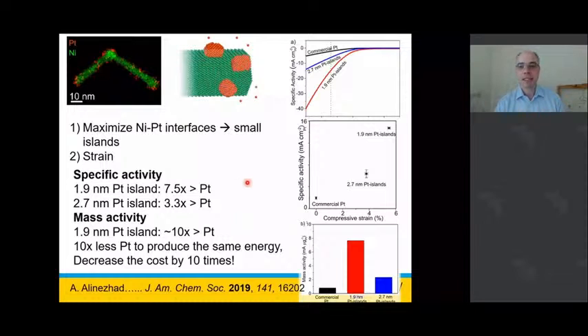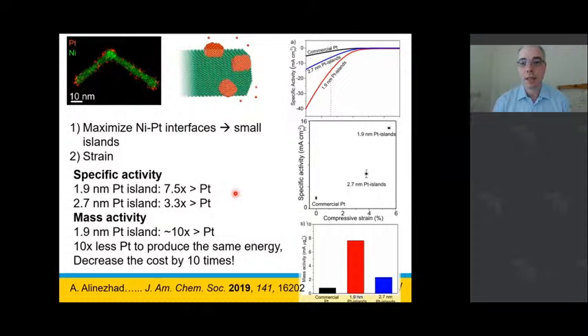And then in terms of the catalytic properties, the particles themselves turned out to be really good catalysts. As I said, we've got these two strategies. We want small islands to maximize our number of interfaces between our platinum and nickel, and the smaller the islands, the greater the strain will be. And if we have a look at the catalytic properties, the small islands are more active, certainly than commercial platinum, and certainly more active than the 2.7 nanometer islands. The small islands were about 7.5 times more active than commercial platinum.